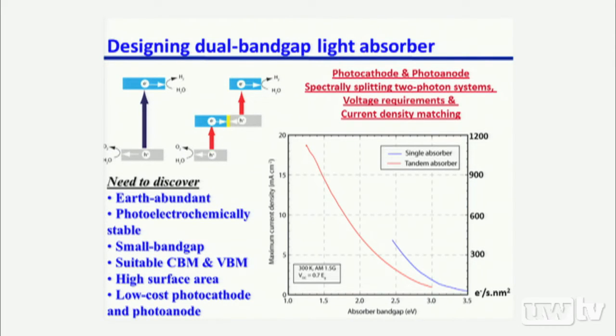Now, this slide illustrates the advantage of utilizing two light absorbing semiconductors compared to the very first example of TiO2 using one semiconductor. If you are using one semiconductor only, just like TiO2, or more recently people are looking at gallium nitride as well, because of the photovoltage requirement, in the solar spectrum you can only utilize the UV region. So theoretically, the maximum photocurrent output would be very limited, because of limited UV photons in the solar spectrum. You can reasonably assume when the band gap is smaller than 2.5 eV, this semiconductor will not be able to drive those two half reactions.